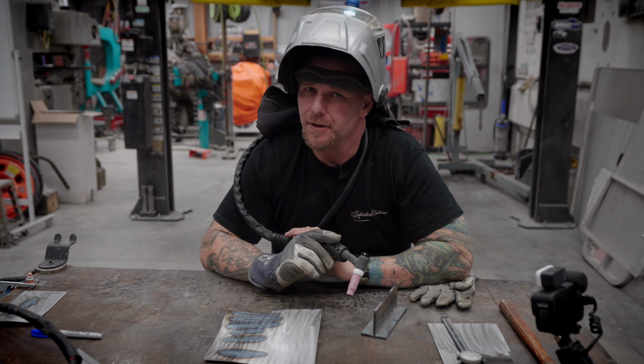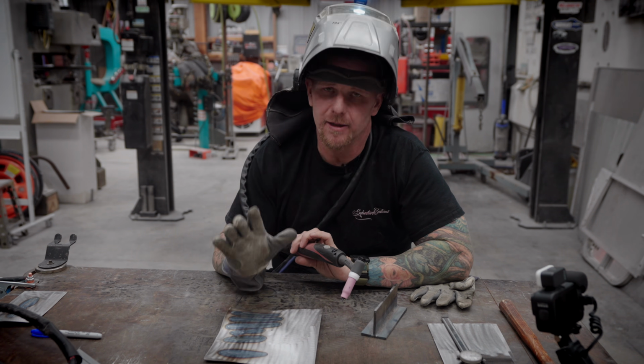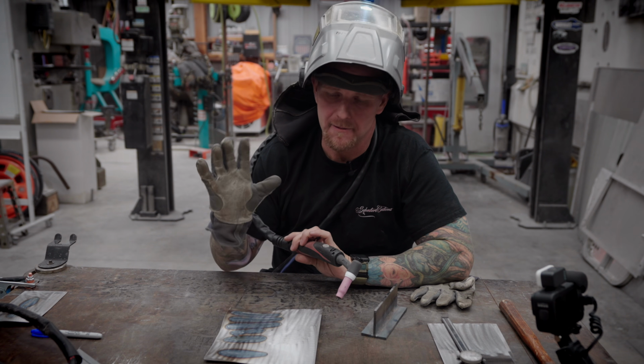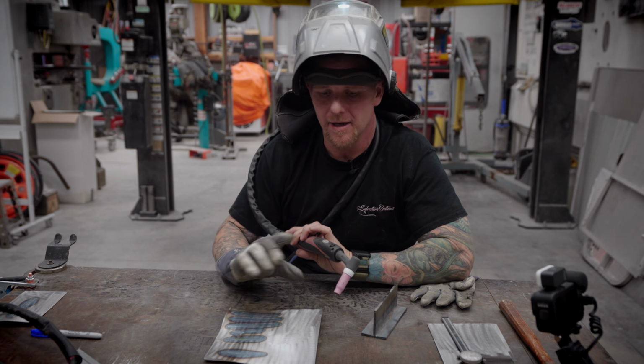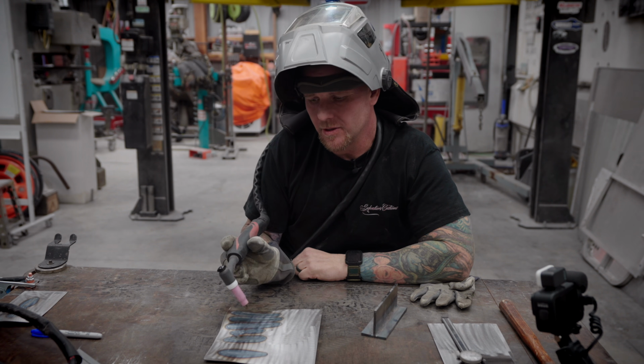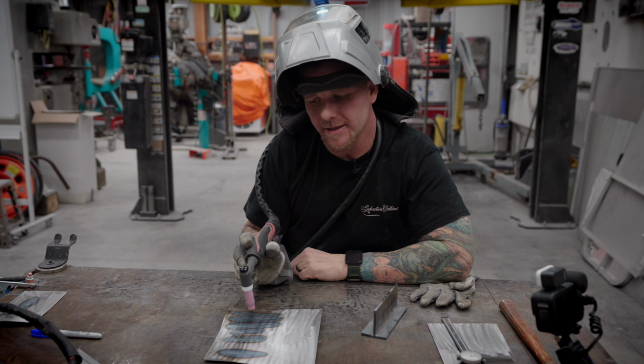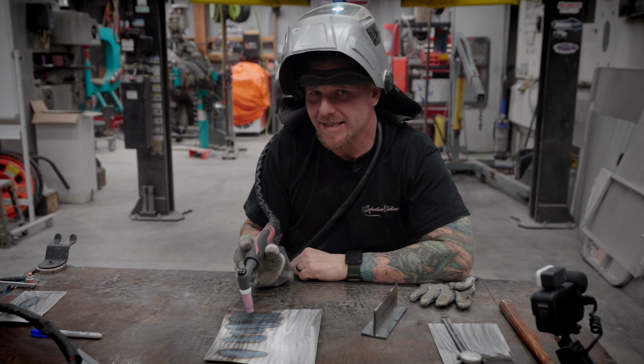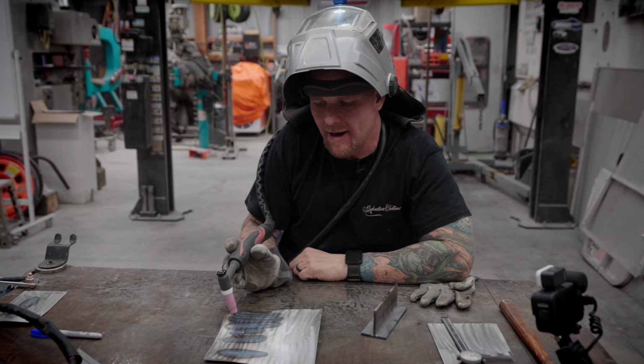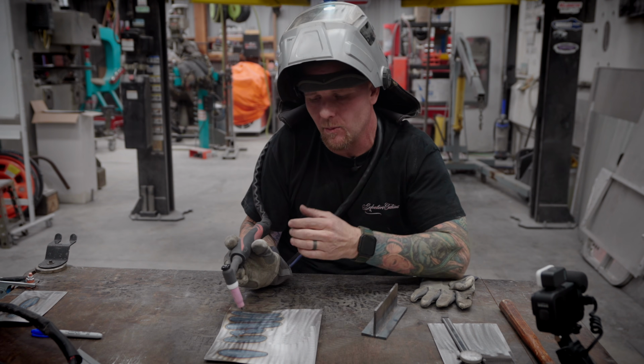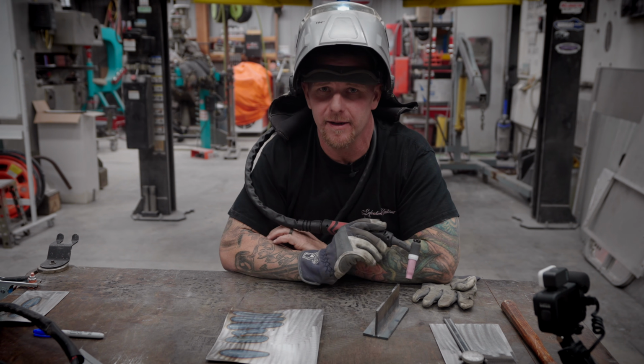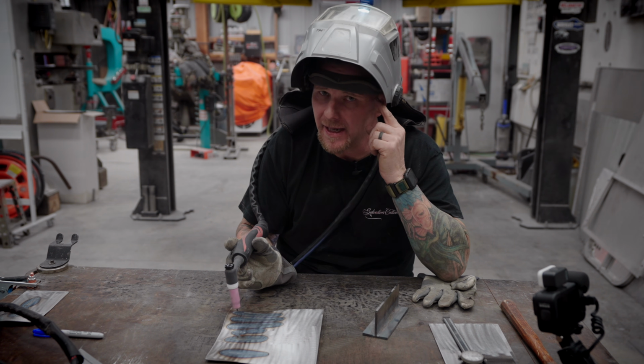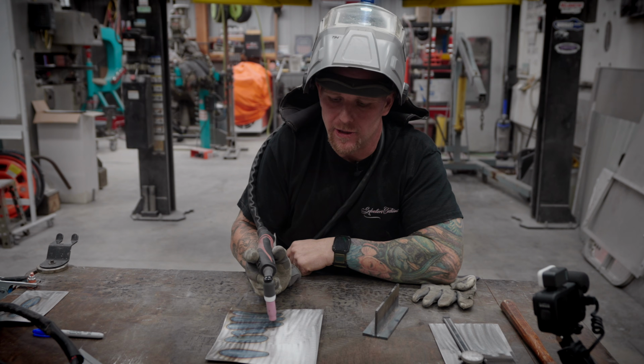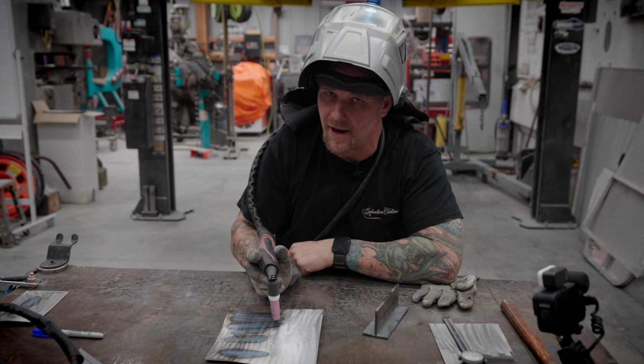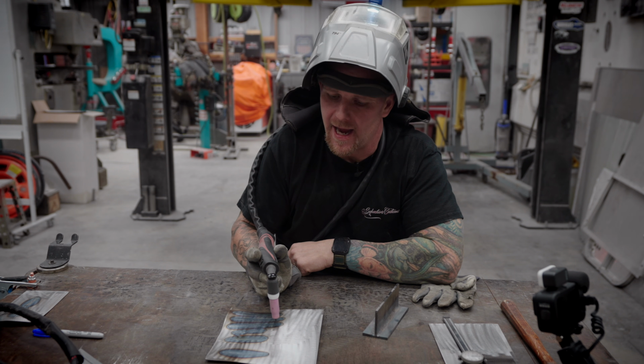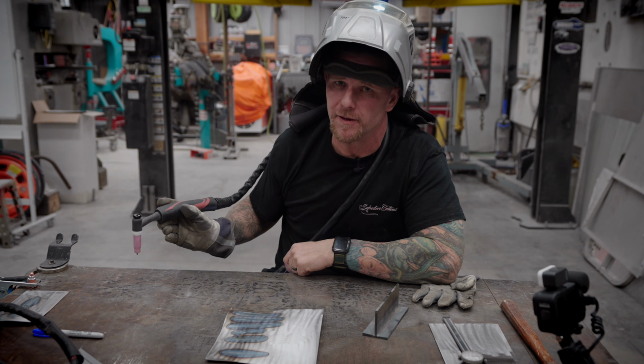Before we jump into the third step, I strongly cannot emphasize it enough to master these techniques, let's recap. Torch angle, 15 degrees. Distance, about a 1/16 away. And a travel speed that has an even puddle with an even heat affected zone. Keep in mind that when you stop, you're letting off the pedal slowly, and then wait for the post flow, and then remove yourself.